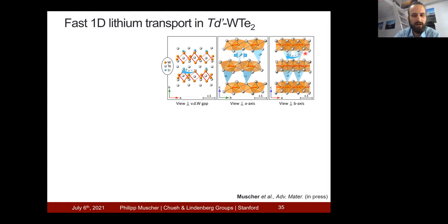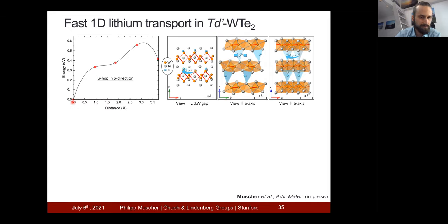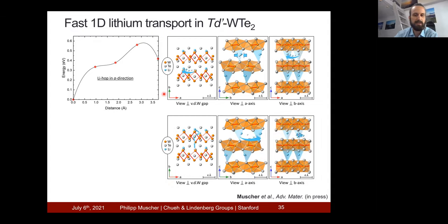The hopping that we see over here is, for example, the lithium ion hopping from one side to the other, shown by this arrow. And you can also see that hop in the top view of the structure. The energy that has to be overcome to make this hop in the A-axis direction is roughly 0.6 electron volt.